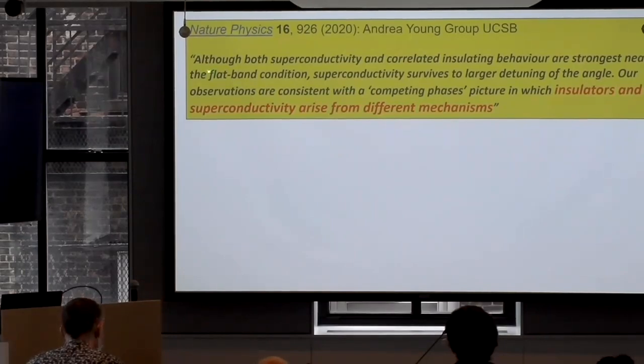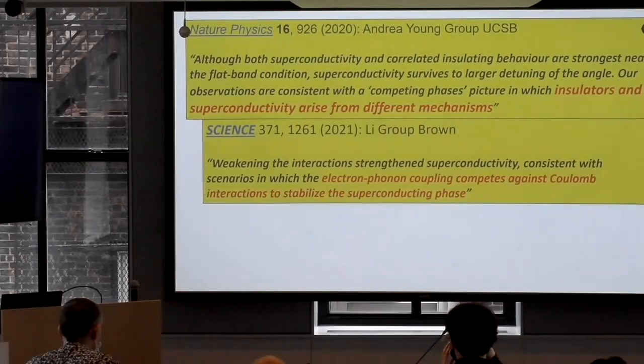So this is one paper. I'm just quoting from the abstract. Although both superconducting and correlated insulating behaviors are strongest near the flat band condition, superconductivity survives to larger detuning of the angle. Our observations are consistent with a competing phase picture in which insulator and superconductor compete. And this is what I was saying, and what Andy was saying happens in cuprates, that superconductivity is preempted by the correlated insulator. If you go to large angle, superconductivity survives and becomes much bigger. But there is a direct experiment from the group of Li at Brown, where he really changed the gate distance in several samples. What he found is that weakening the interaction strengthens superconductivity, consistent with scenarios in which electron-phonon coupling competes against Coulomb interactions.